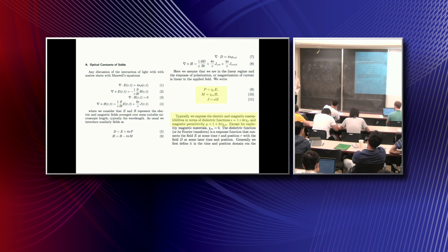So this kind of thing is done all of the time. We use it all the time in fitting response functions. We're going to fit to the complex conductivity here and make some physical arguments about the fact that the real and imaginary parts are related to each other. We can use it to infer the superfluid stiffness of a superconductor from doing a finite frequency measurement, so we can know the phase stiffness of a superconductor. We're going to talk about that, how much strength is in the conductivity delta function at zero frequency, from measuring at finite frequency. So this kind of thing is going to happen all of the time, and we're also going to use it for various kinds of sum rules that are important to our analysis as well.